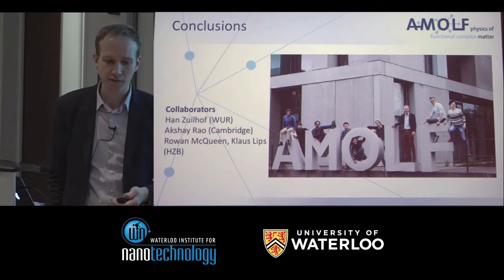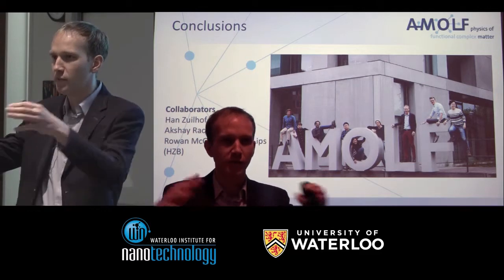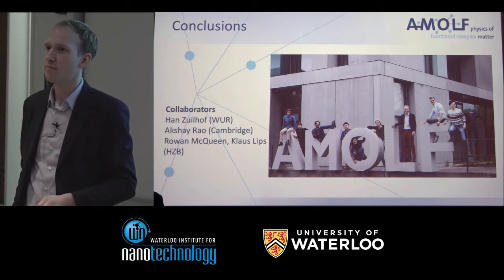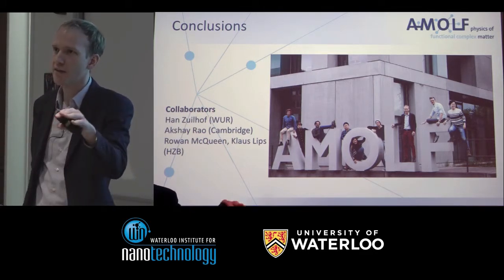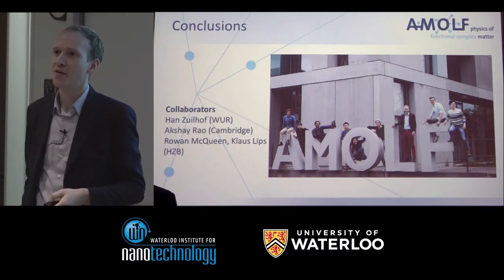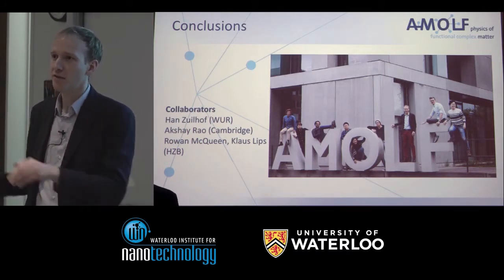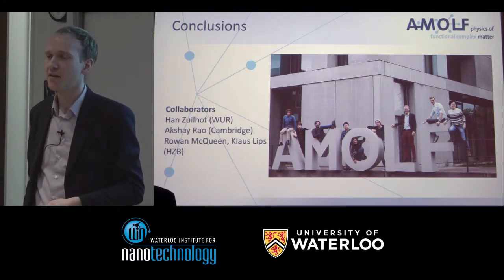The biggest challenge, I think, is that all silicon cells are textured to capture more light, because silicon otherwise is very reflective. So you texture them to make them rough to grab more light. And processing onto that is basically not possible. So you have to get a flat silicon cell. But you still want the light capture, right? So you have to do some clever light management to capture the light in silicon while still having a flat surface. You could texture the top perovskite layer. But that's something that's still, I think, a challenge.